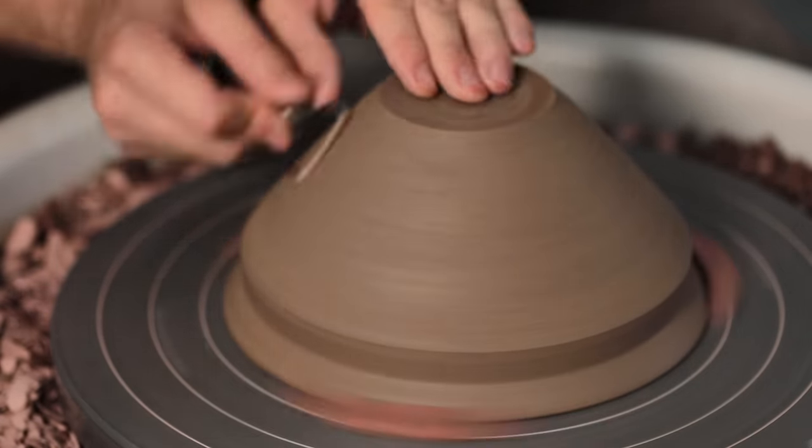Here's that grogged pink bowl I started with, amongst many others. And now, the final step before they're actually finished is to sand the bottom of each pot to remove the coarse specks of grog that always appear, even if you've burnished the clay, because as the clay fires, it shrinks more than the particles of grog which have already been fired. Which means, even if you spent time at the leather hard stage burnishing the clay to be glassy smooth, once fired, that smooth quality is going to be lost to some degree, and it will need to be sanded, albeit only gently, at this stage.